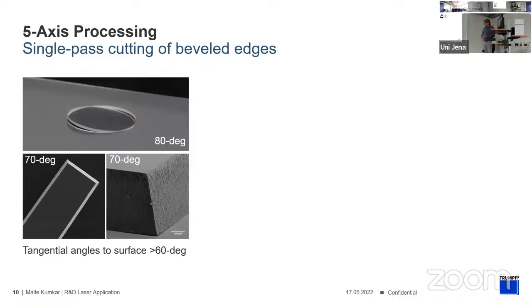Another thing is how to release inner contours. The process is a zero gap cutting, so it's how to release inner contours. One way is to tilt the modification, and you can do this up to a certain extent. This, for example, is 80 degrees instead of 90 degrees, and this allows to release these inner contours out of the system. And for others, it's helpful for design reasons.